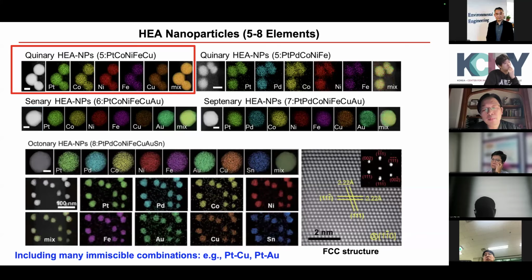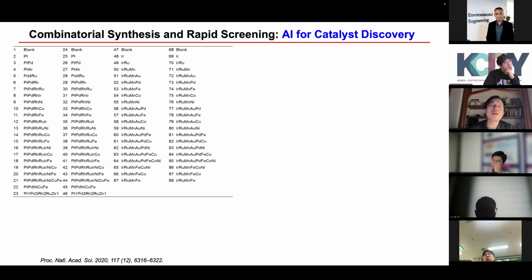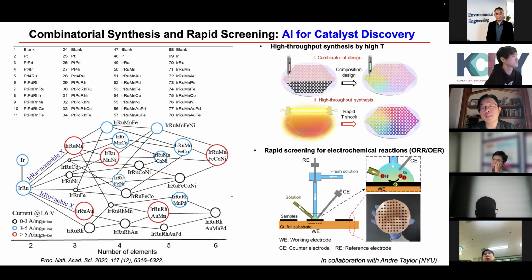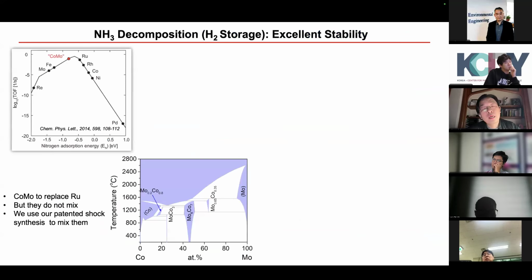Yeah. So we can mix platinum and copper, for example, they usually don't mix. Now, in this case, they will mix. So now, without any constraint, you can start to design your catalyst. You can just keep adding elements, and you can make it using this shock method. So this is really important for what is called AI for catalytic discovery. And you don't have a lot of constraints when you design elements. And with rapid screening of the catalytic performance, we can basically quickly discover the optimal composition. Yeah. So this is another real example case funded by DOE again.